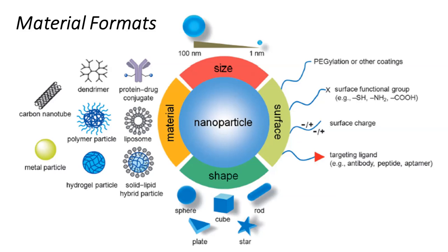However, a lot of the more recent articles on polymers for drug delivery recommend that the diameter of these polymer nanoparticles should be in the range of 40 or 50 nanometers. This allows them to stay in the bloodstream and not penetrate through endothelial cells in blood capillaries and arteries and such. However, when they come across the leaky vasculatures of tumors through their navigation through the circulatory system, they're able to leave the circulatory system through these pores, essentially these nanometer-sized pores. They're able to slip through and target the cancerous cells from within. So that's obviously a huge advantage.